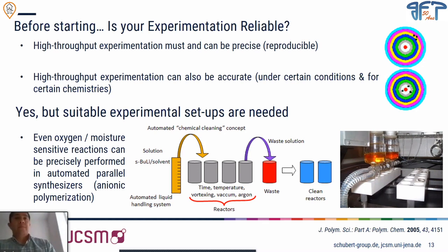After some time, we take out this solution, we rinse with new solvents or distilled solvent or dry solvent, put it into the waste, and at the end we achieve, let's say, somehow clean reactors, right? Once you make sure that the reactors are properly conditioned to make the chemistry you want, you can proceed with the experiment in a more reliable way.